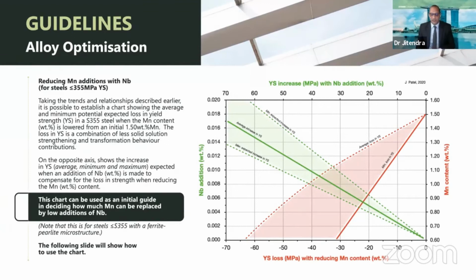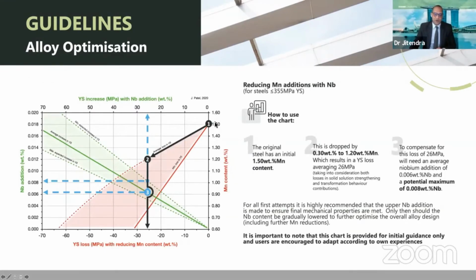I'm not going to talk about this too long here, but what we've got in this presentation, which you can have, and as I said it's in the paper, is a set of guidelines I've created which give you an idea of the sort of savings you can make in alloy content as you want to decrease the manganese content. I'll just run through this quickly. So this is an example of 1.5 manganese. If you want to reduce the manganese content to 1.2, it gives you an idea, by following the red line as you come down, how much drop in strength you will get from the reduction in manganese. So in this case, by dropping it by 0.3% manganese, we go from 1 to 2, and that on our chart means that we're dropping about 26 megapascals.